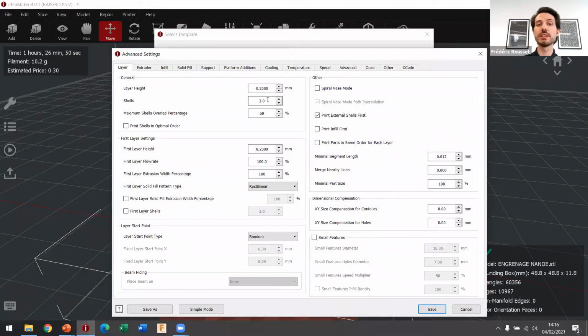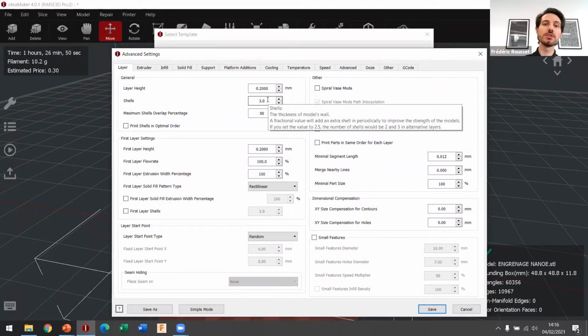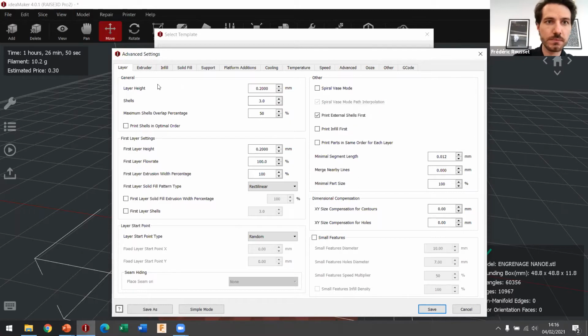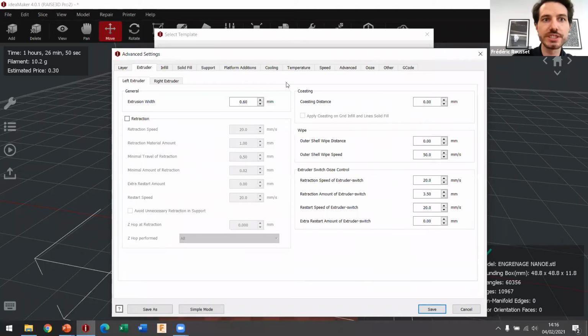For the shells, I recommend 3 shells. This is the best. You can do 2 shells, but it can be a bit brittle. So I recommend 3 shells for the H13. So this is it for this part. For the extruder, the extrusion width is set at 0.6 for the H13. You can go from 0.4 or 0.5 to 0.8, depending on the size of the nozzle. You want it to be a bit more than the size of the nozzle, so it can smash a bit more on the bed. You don't need any retraction for the metal. You don't use retraction because you would do some back and forth in the extruder and you don't especially need it, so it is safer to not do it.